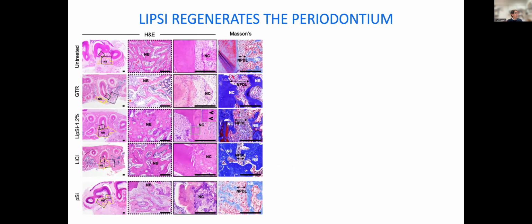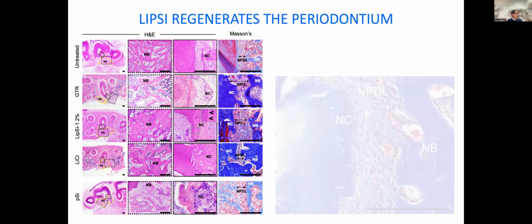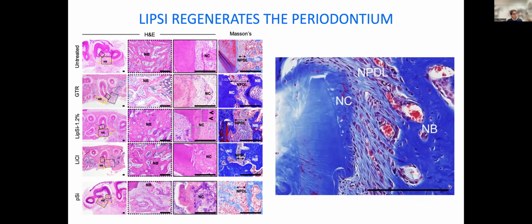Very importantly, we not only regenerate the bone, but if you look at this part here, we form new bone, we form new cementum and new dentin here, and we do form a significant amount of new periodontal ligament at 2 weeks already. And if you look at the structure of how this is organized, you do see that the bone forms and the ligament anchors into the bone on one side and into the new cementum on the other side, which is what you would want for the regeneration of this complex interdigitated structure.